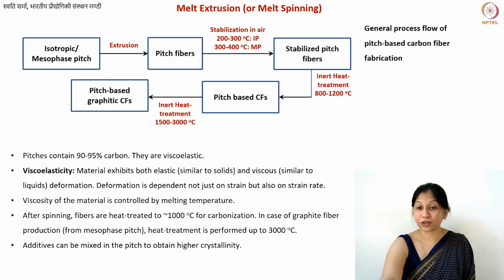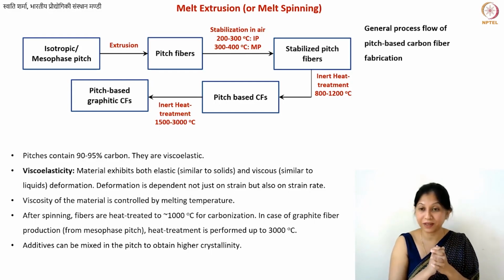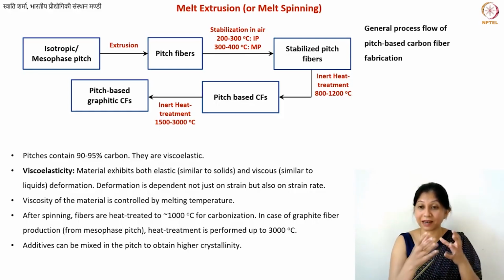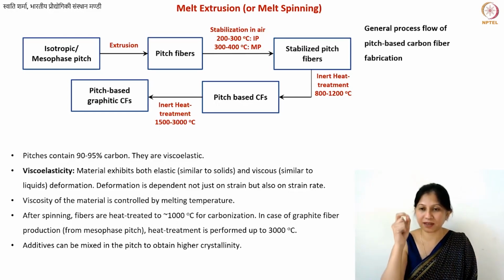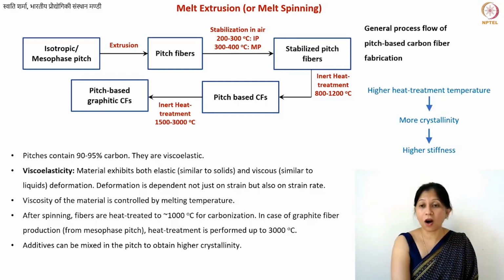But of course, you need to remember that you need to have an optimum concentration of the additive, and also the size of the additive, because you remember that you were filtering out these solid particles. So if you add bigger solid particles, then it will block the capillaries. So you need to have only very small additives in terms of size, but that is also possible.